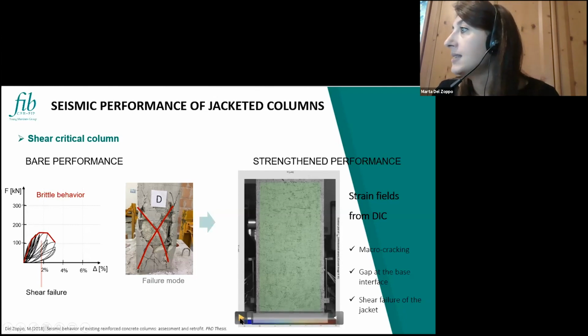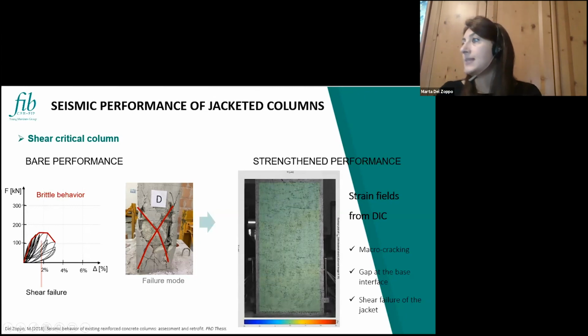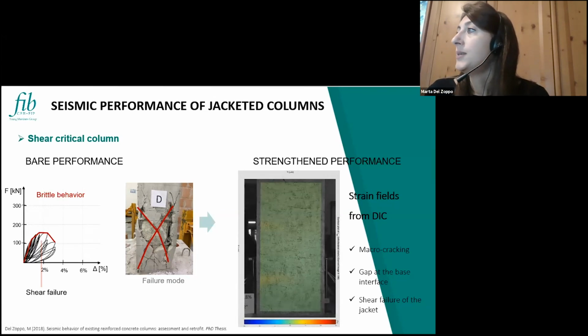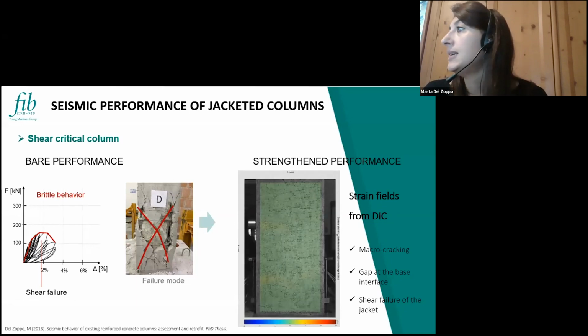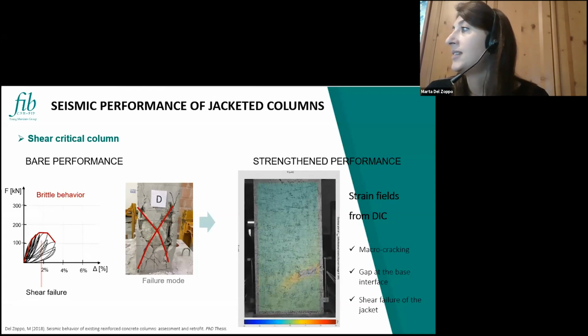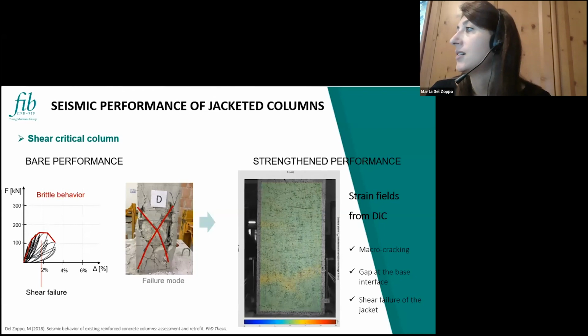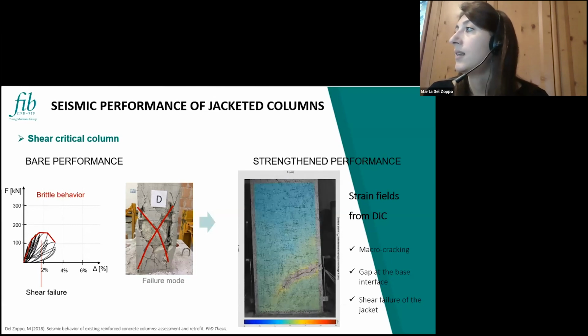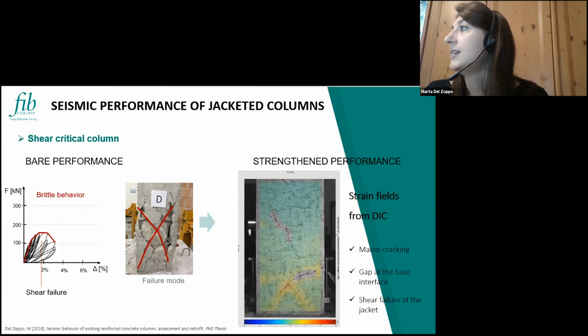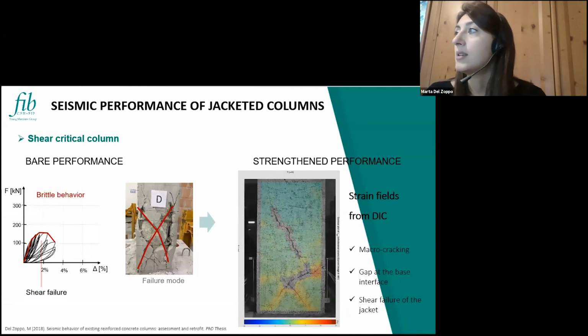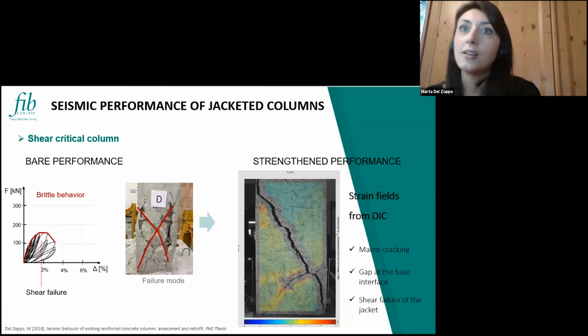Now let's see, also for this case, the behavior of the jacketed specimen. Also looking at the DIC records, the strain fields, where the yellow areas are the tensile strains concentrated where the cracks are developing. We can see, since the beginning, this rocking behavior around the base of the column, the foundation interface, and the opening of the first flexural cracks, so flexural behavior until now. Then we have the first opening of the diagonal crack due to shear. The fibers are working to bridge the crack, so to close that crack, until we have the final opening of the jacket caused by the shear.